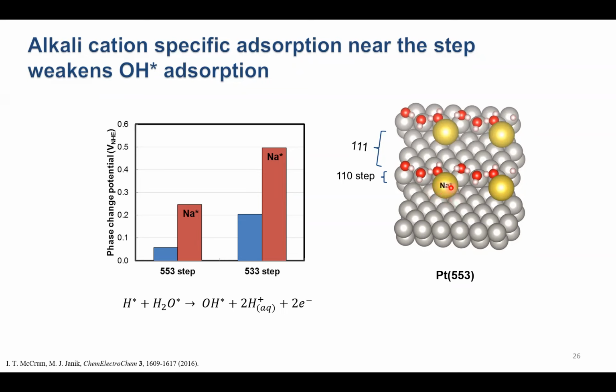Further, once we put it there, we find that it has a big effect on the adsorption energy of hydroxide in water. Basically, because this cation does not transfer an electron, it retains most of its positive charge, and it kind of tries to steal the solvation from this adsorbed hydroxide, and it disrupts the strong hydrogen bonding between the co-adsorbed hydroxide and water on the step edge. And so now when we calculate the potential to go from a hydrogen covered step to an OH and water covered step, that's shown in blue here, we can see for both step types, the presence of an alkali metal cation, in this case sodium, shifts that peak to more positive potentials. And that's exactly what we see when we increase the pH experimentally.